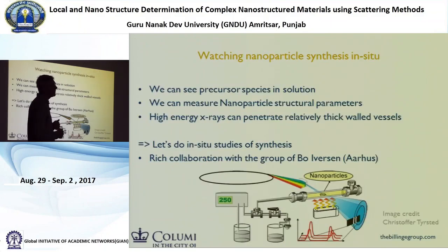Once you have that idea, you can try and do an in situ synthesis. So you can take a reactor with reagents in it, and then you flow the reagents through a tube, and then you bring the synchrotron beam in to the side, put it through the tube, and you can do a time resolved measurement of the synthesis of the material in real time. So this is a hydrothermal synthesis. It's a collaboration with Bo Iversen in Aarhus. So we often collaborate. We're basically the scattering experts, and we collaborate with people who have their own expertise, and this is how a lot of our work gets done.